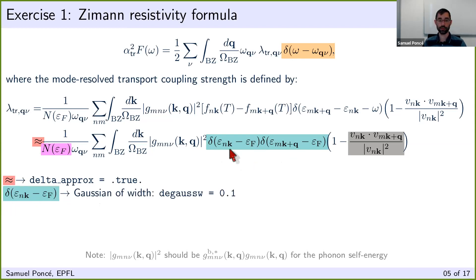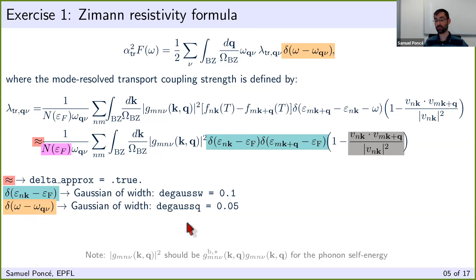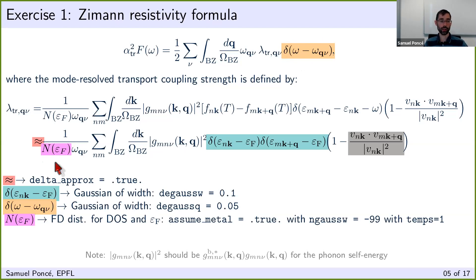The Dirac deltas are defined by the input variable degaussw, which is simply the width in eV — 0.1 eV in this case — for the Gaussian delta on the electronic eigenstates. There is another Gaussian delta on the phonon frequency, controlled by a different input variable degaussq, which is typically a bit smaller — for example 0.05 eV here.